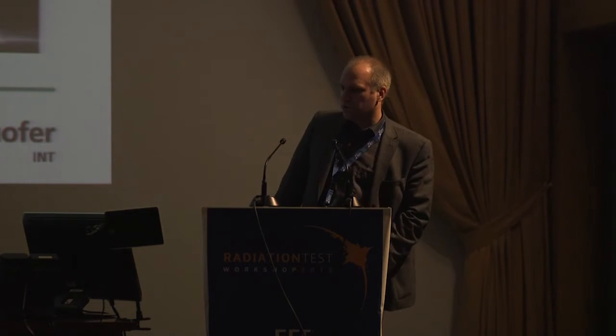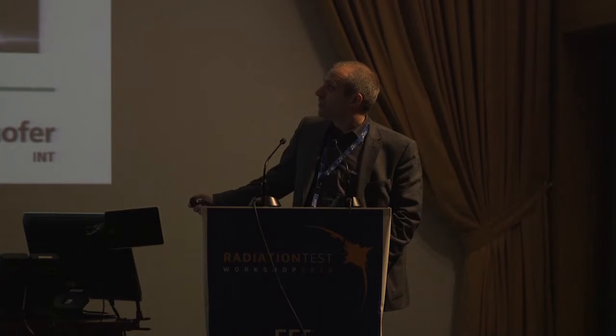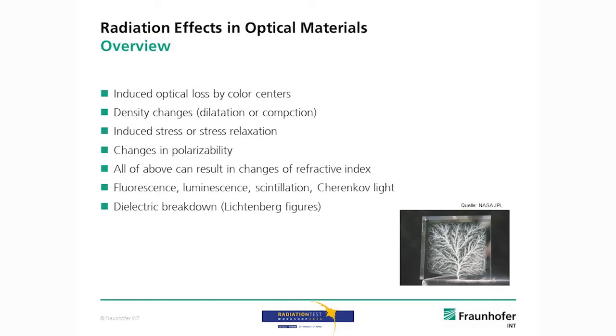optical power, or induced attenuation of the materials due to radiation by color centers. But there may also be density changes, or stress relaxation, or changes in the polarizability of the materials. And it's interesting to know that all of the above can result in changes in the refractive index. So if you look for radiation-hard glasses that are optimized for optical loss, and you're very dependent on the refractive index, then you might not have the best glass.